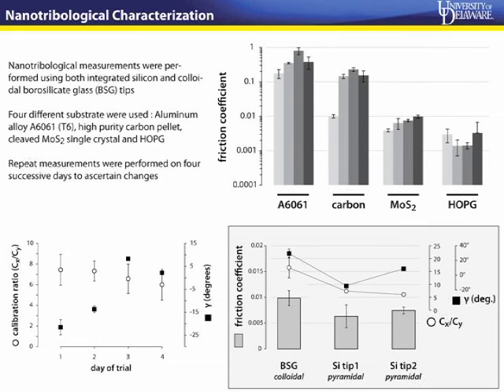So you'll notice that the error bars are pretty small, and you do see a general trend between the different samples: the aluminum, of course, has higher friction, and HOPG in this case has the lowest friction. Plotted here are the calibration constants and the gamma that we obtained for these 4 days of testing.